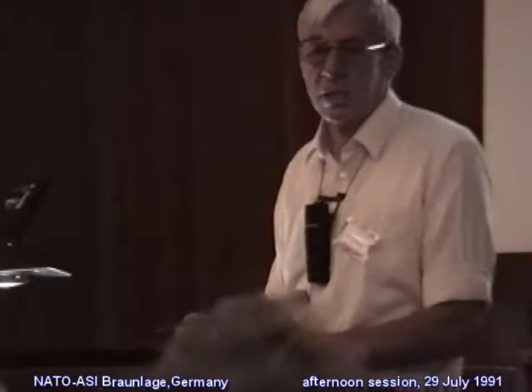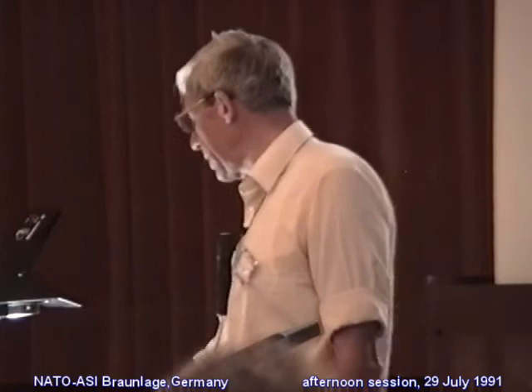And that again gives intellectual problems in understanding failure, because even if one does initiate a crack through flaws in the material, there is still this hydrostatic pressure forcing the faces of the crack together. There are real problems in trying to understand the way in which cracks are propagated within the contact stress field. Those are things we can discuss later.